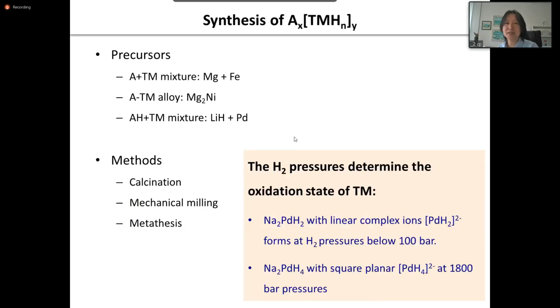Regarding the synthesis, there are a few ways. I just picked 3 representative ways. One is to mix an alkaline earth hydride with a transition metal and heat them under high hydrogen pressure. Or you can start with an alloy, or a mixture of alkaline earth hydride with transition metal, and calcine at temperature and pressure. You also can apply ball milling. You also can do metathesis. And I'd like to highlight one thing here, that the hydrogen content in the complex hydride would in some cases depend on the pressure applied.